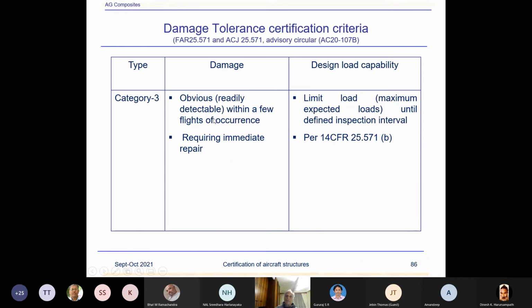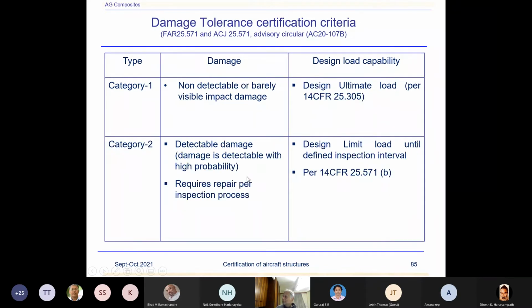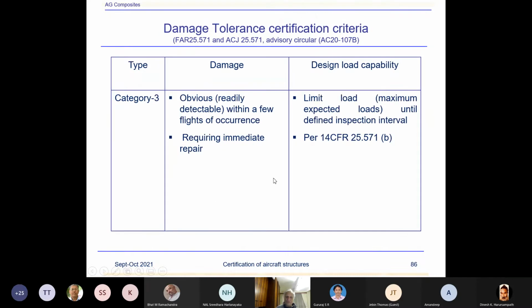Category 3, obvious, readily detectable within a few flights. When such large damage is there, like 6 inches, depending upon the criteria. In fact, I'm just quoting 6 inches, it could be 4 inches or more. Readily detectable within a few flights of occurrence. So what happens in this one? This damage doesn't have to wait for inspection intervals. When during walk-around inspection such a large damage is seen, the aircraft will not be allowed to fly until repair is done. In category 2 it is 2 inspection intervals, but this is only within a few flights of occurrence, so requiring immediate repair. So that is the difference between category 2 and category 3 damages.